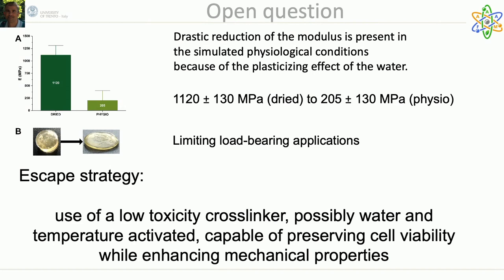I'm referring to the drastic reduction of the Young modulus observed when the sintered material is exposed to simulated physiological fluids. Young modulus values in this case dropped from a maximum of 1100 MPa when dry to a low 200 MPa in physiological conditions, caused by water absorbed and acting as a plasticizer inside the material. This fact could strongly limit some applications in bone tissue engineering, especially when load-bearing is required.